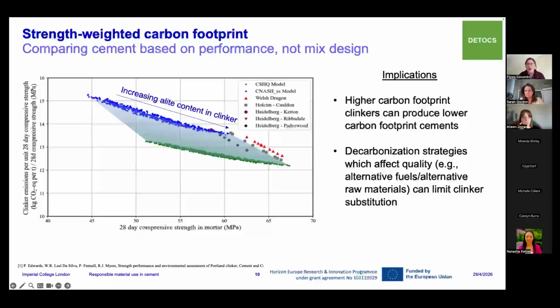And when we look at that on a unit strength basis, the best emissions per strength results come from the higher strength systems, which have the higher alite content clinkers, which highlights the same thing we saw with the clinker substitutes, that higher emission materials can produce lower emission cements depending on how we use them.